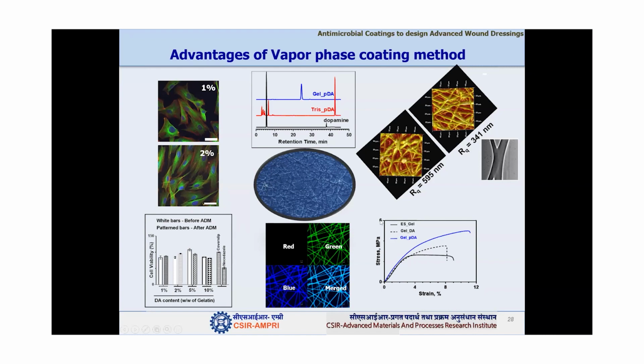Then this is the mechanical plot, the stress-strain plot. You can see here that once we cross-link the gelatin nanofibers using polydopamine, the mechanical strength, the tensile strength of the nanofibers as well as the elasticity of the nanofibers, they got improved. Even the roughness also got reduced after coating. So all the results are quite interesting.